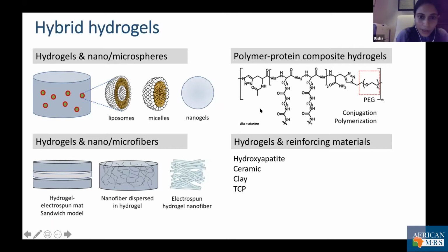Other types of hybrid hydrogels are polymer-protein composite hydrogels. They have been synthesized by either conjugating the protein on the backbone of the polymer, or by polymerization with two solutions of polymer and proteins. The presence of proteins induces self-assembling properties in the hydrogel system. Also, hydrogels have been incorporated with reinforcing materials, especially for bone tissue regeneration, so that you improve the mechanical properties. So hydroxyapatite, ceramic, clay, and TCP have been added to these hydrogels.